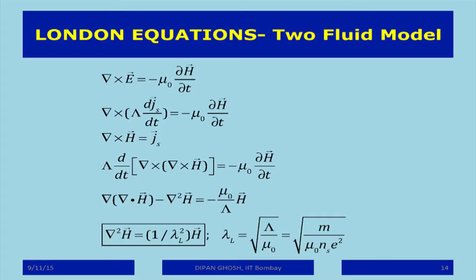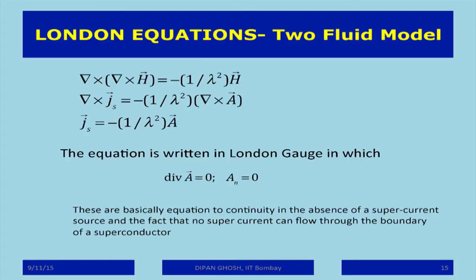But if you now choose that, look, my del dot of H equal to 0, then this gives me an equation which is del square H equal to a constant which I have defined as 1 over lambda square H, where this lambda with a subscript L is known as the London penetration depth. So this is the second London's equation. Okay, this is what I did.